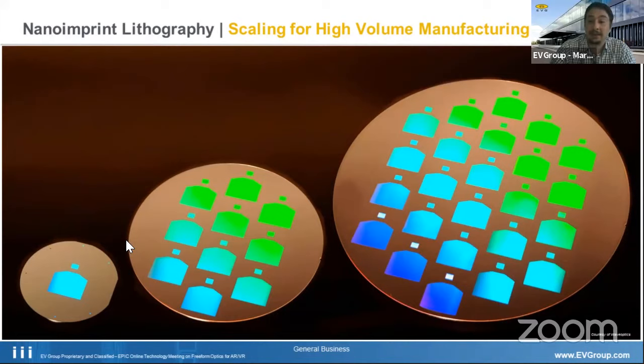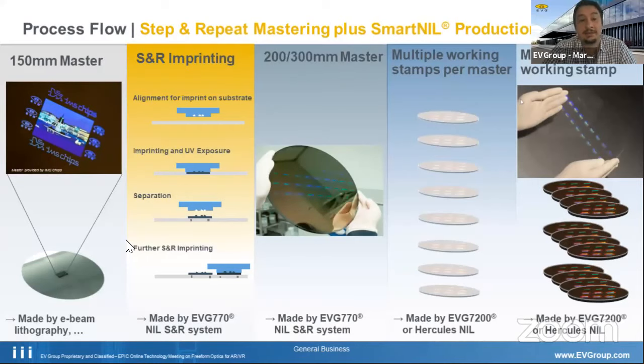And basically what we can do here is go through this whole process, starting off with such a single die. This time, of course, we don't show details of the design of the structures. That's proprietary WaveOptics, but we have a very nice reference design. And here you can see it also starts off with a single die, which you make by E-beam lithography and etch into the wafer. And then we go for the step and repeat imprinting. So we do the nano imprinting just one by one, taking one die, do exposure, separate and make the next one until a 200 millimeter or even a 300 millimeter master is filled. That's the so-called step and repeat master.